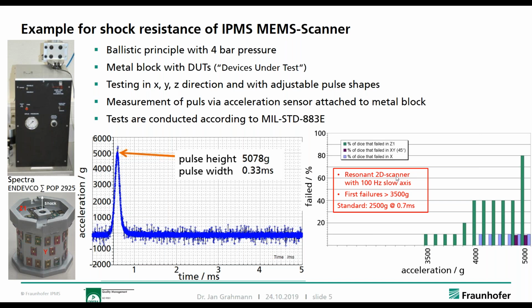So here we used that resonant 2D scanner. I showed you the slide before, and one specific characteristic of that scanner is that it just has 100 Hertz resonance frequency on the slow axis, which means that this is a quite soft spring used for the mirror. And what you can also see here is that our standard is that our designs, unless our customer wants to have something else, at least have to withstand 2,500 G of pulse height and a pulse width of 0.7 milliseconds. And now looking at that graph, you can notice that this quite soft scanner was well beyond these 2,500 G, actually going up to 3,500 G, where you have the first 10% of devices under test failing. And then, of course, with increased pulses, more and more devices start to fail.